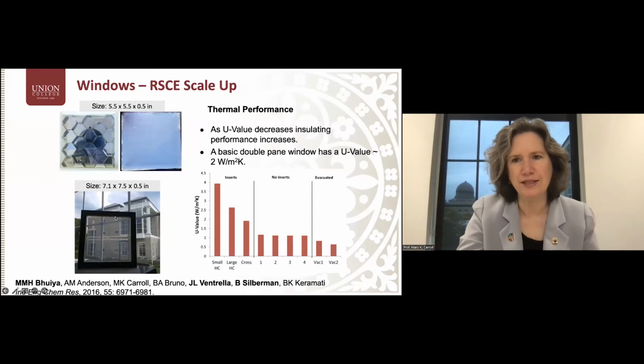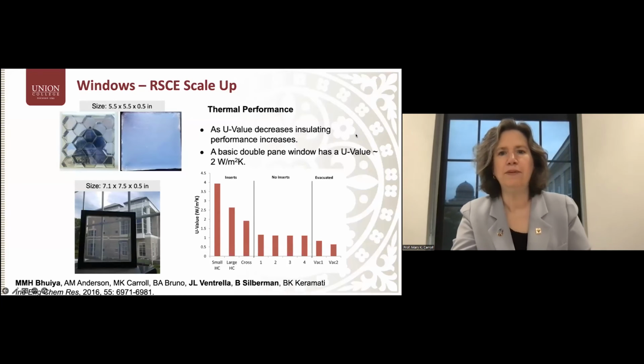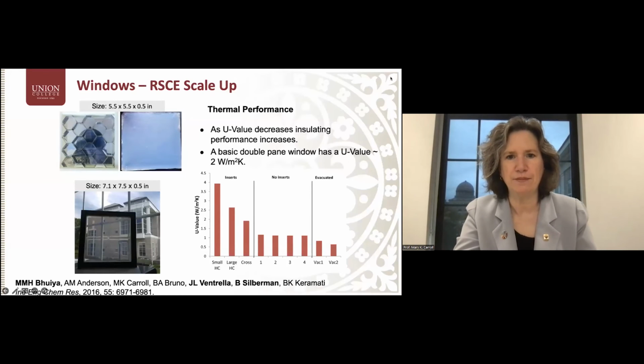We've been able to make some small prototypes. This one involves 4 aerogel monoliths sandwiched between 2 pieces of glass in a frame, and you can see through it with pretty good optical clarity. It's not as transparent as the window glass that's right next to it, but the thermal performance is very impressive.